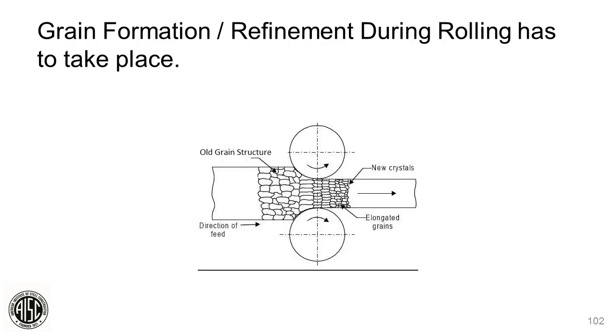And that's done through grain refinement in a rolling mill. The melt shop, of course, gives us our vanadium, columbium, and nitrogen levels that we need for those grain refiners to work, and also the manganese. But work is another important aspect of what's needed. Products that don't have a lot of reduction on them would need more alloys. Next slide.